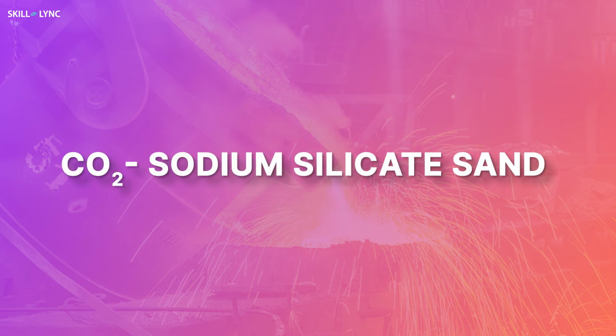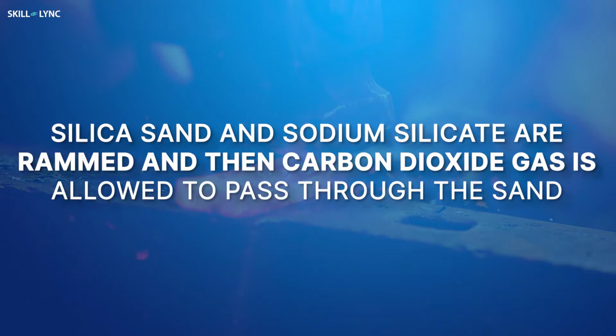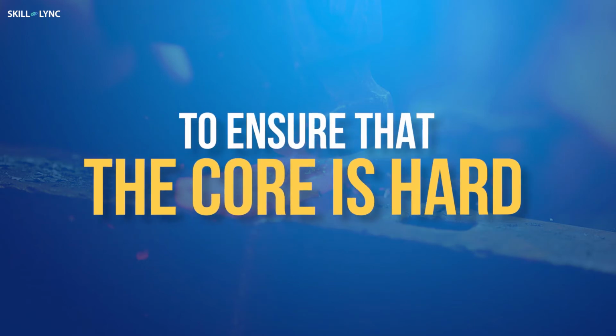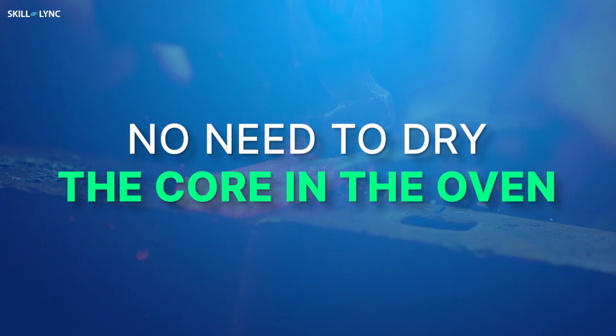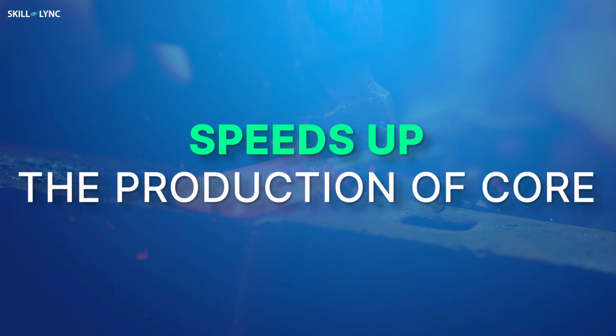CO2 sodium silicate sand is another important sand which is used for making core. During the production of core, silica sand and sodium silicate are rammed, and then carbon dioxide gas is allowed to pass through the sand. This is done to ensure that the core is hard. By doing this, the need for the core to be dried in the oven can be eliminated. Hence, using this sand enhances the speed of core production.